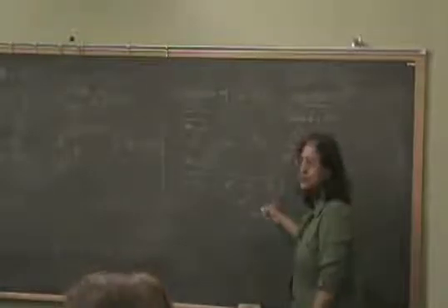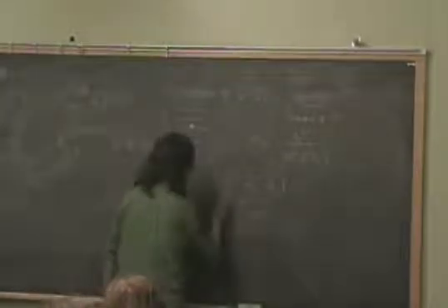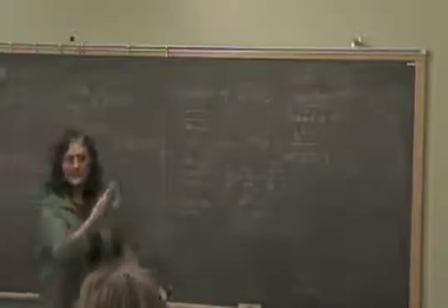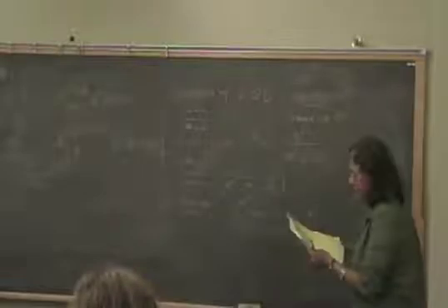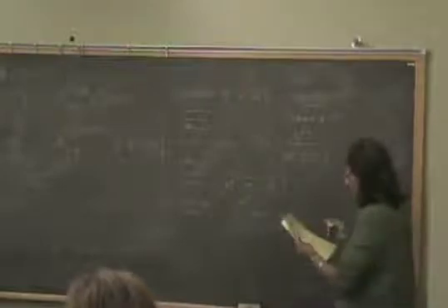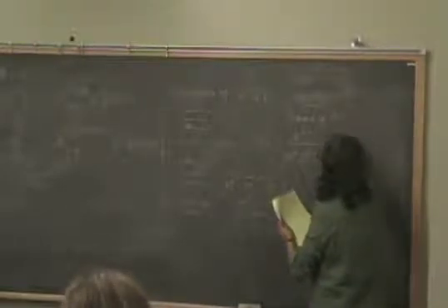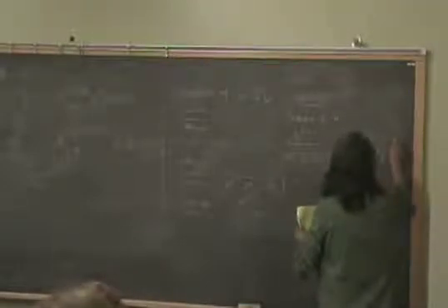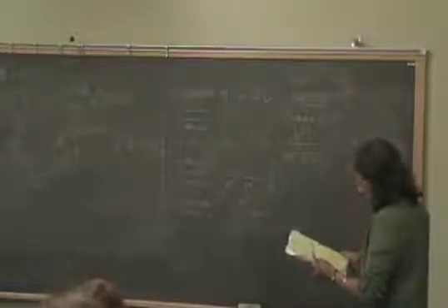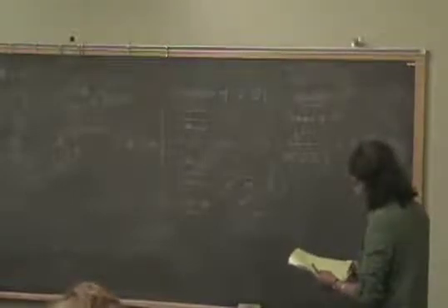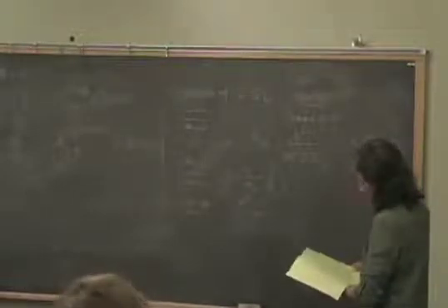But let's say if you had to pick something, this is what it would be, and now m star is the reduced mass of this duo. Right? You go into the center of mass coordinate, relative, etc., and then this is the reduced mass. And then here's the dielectric function. Again, you can worry it's a quantum dot, on the scale. What are you calling a dielectric function? All these things need to be revisited, but you end up getting this. Okay? So for typical values of epsilon naught and masses and so on, this ends up being a very large scale. Why don't I have that scale here?